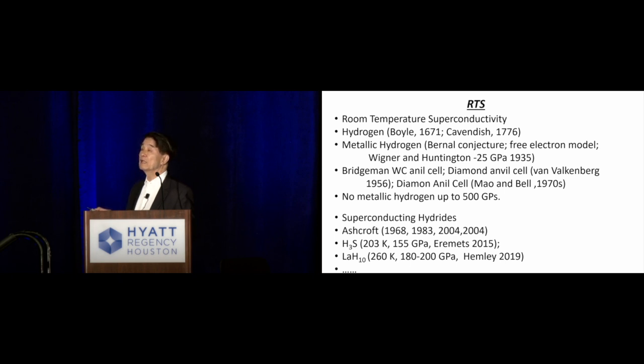At the time, people could not get to that high pressure. Later on, people used Bridgman's method to get up to 50 GPa, and then later using the diamond anvil cell, got up to almost tera GPa, but they had not been able to get it into metallic form. In spite of that, a few years ago, a group of people from Harvard mentioned they got metallic hydrogen up to 500 GPa, but they claim they only saw it once, and then it disappeared. So therefore, it's still a question.